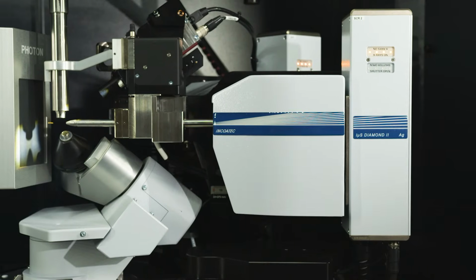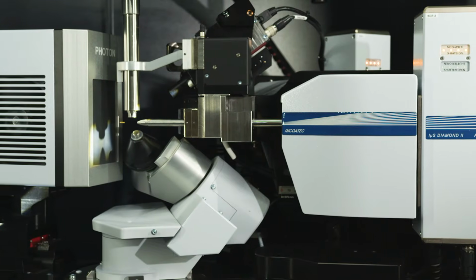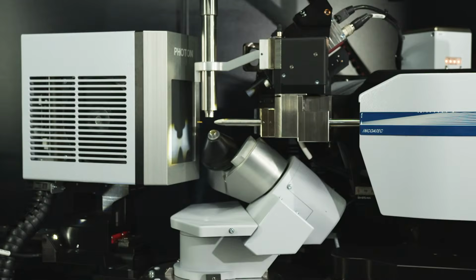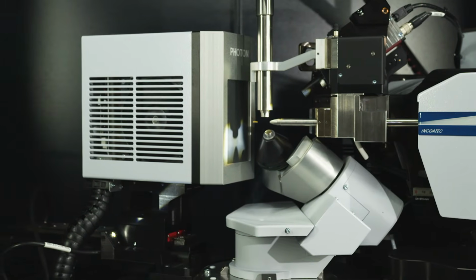All right, so we got that really great source, and in the video we had also seen you have this very nice optic, custom made to really couple to it. But if we go to the other side of the sample, now we're talking about detector technology, right? Because there we've also had kind of a little bit of an issue with higher energy wavelengths. The advantage of modern CPAD detectors is that they use a high Z scintillator, and that's super sensitive for silver radiation, for high energy radiation. That's very different from silicon detectors, HPC detectors, that just do not work for molybdenum or silver, because silicon is not a good sensor for silver. Almost 70% of the X-rays will just pass through a silicon sensor.